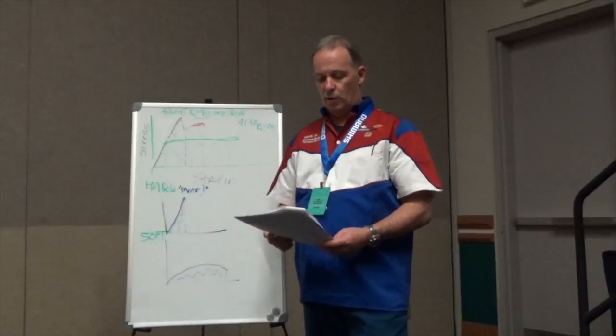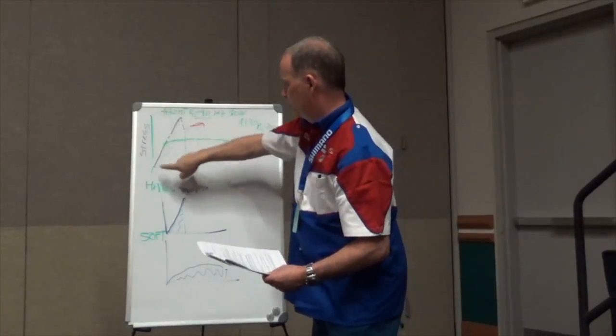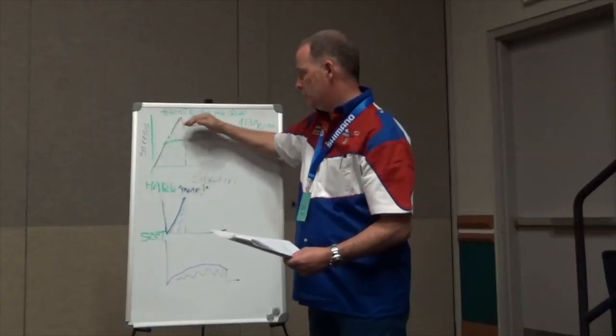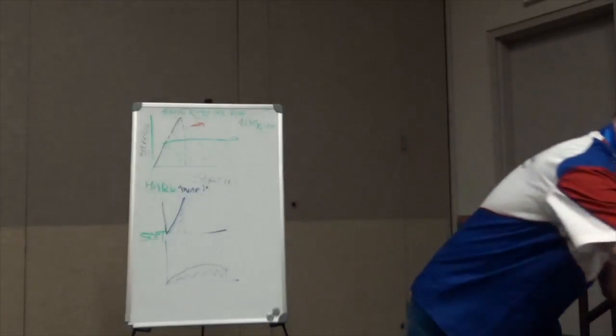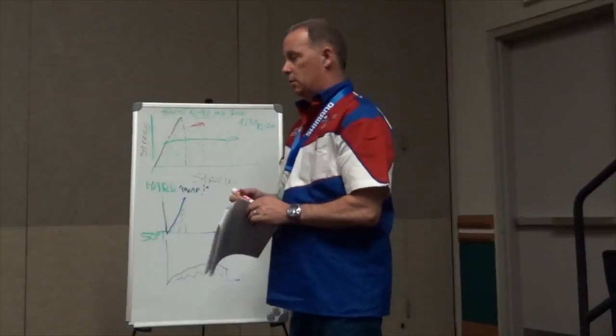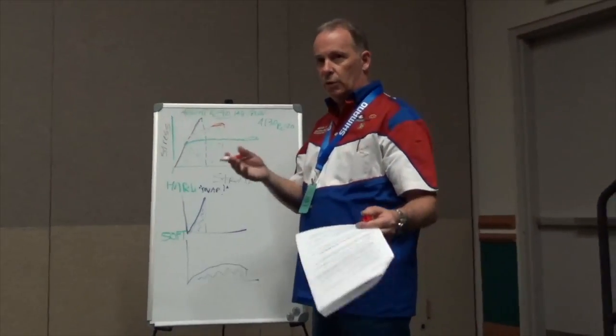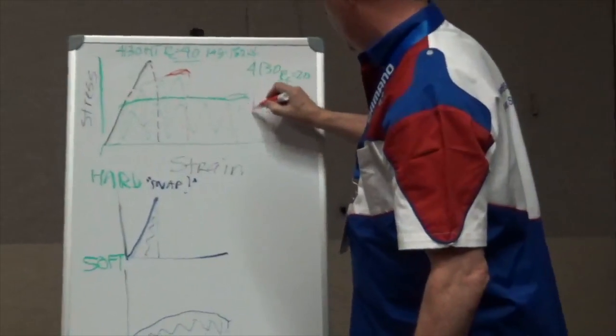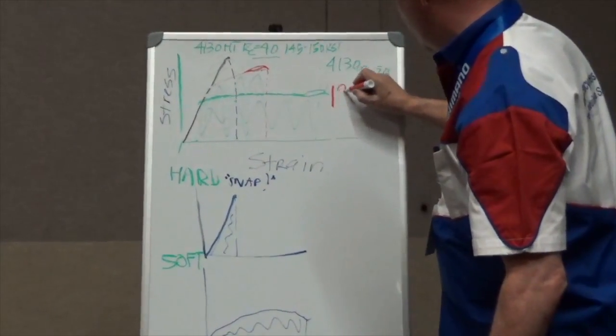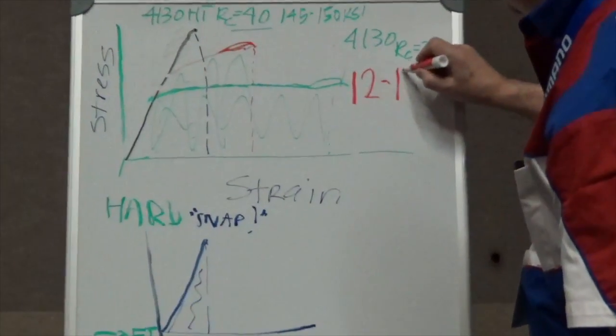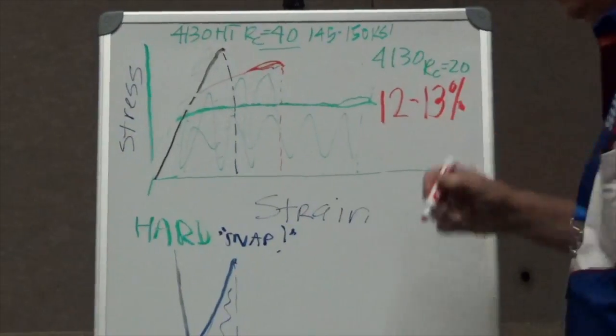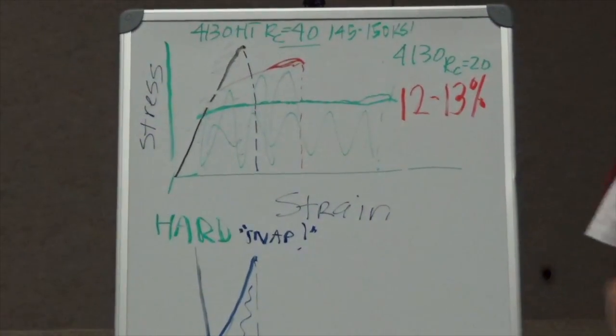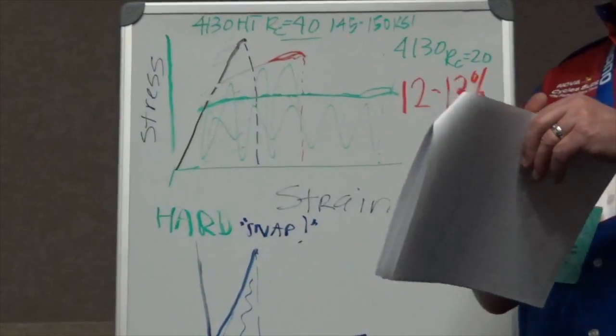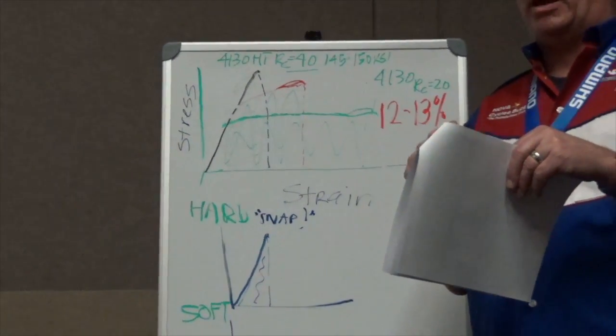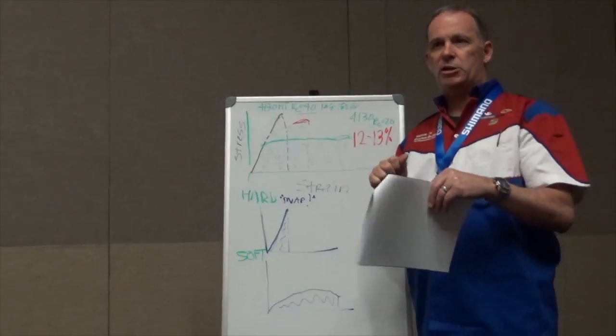So what actually happened is that the materials that had a specific ductility, remember I was talking about optimizing. Well, the materials that had the best ductility have what I think of as a holy grail number. Again, none of the manufacturers tell you this stuff. We just learned it by doing a university test. The holy grail number for ductility as measured by elongation is 12 to 13%. What that means is that the material will change its dimensions by 12 to 13% before it fully fails. That's how much stretch and tear the material needs to have.